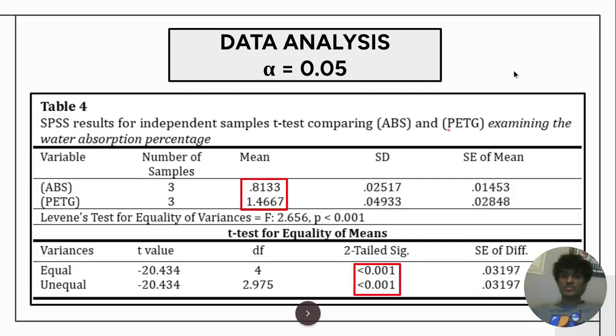In terms of the water absorption percentage test, ABS had an average percentage of 0.8133, whereas PETG was about 1.4667, and the p-values were below 0.001, again far below the 0.05 alpha threshold, indicating a statistical significance between these values, also indicating that in terms of water absorption percentage, ABS absorbed less water on average and is better suited in terms of being in water.